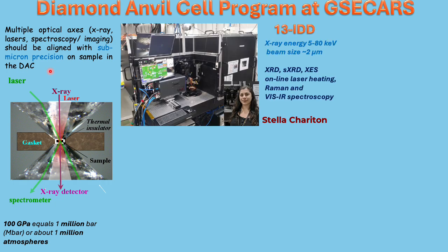At GSECARS, we have 3 beamline stations where we are running a diamond anvil cell program. Main of them is 13 IDD, where a high energy X-ray is focused down to less than 2 micron. And mostly we are running X-ray diffraction and X-ray emission spectroscopy technique combined with online laser heating, Raman, and visual infrared spectroscopy. And we can run samples in the entire range of crystallinity from amorphous to nano to polycrystalline and single crystal. And Stella Chariton is the main person to contact to run experiment at IDD station.